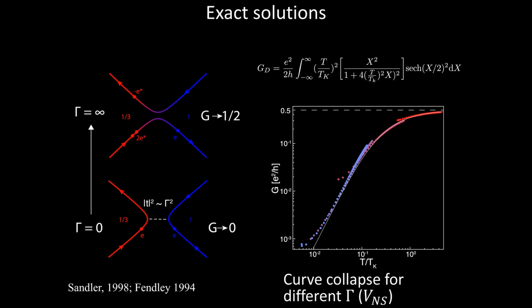So here you're trying to tunnel whole electrons into the 1/3, but if you glue these two together, you might think that the dominant process is that I have to wait for 3 quasi-particles of 1/3 charge to come to the junction, and then they'll turn into a whole electron. One side of these has quantized charge e/3, the other has quantized charge e. Maybe you wait for 3 of them to come and jump across the junction at the same time. That turns out not to be the dominant process.